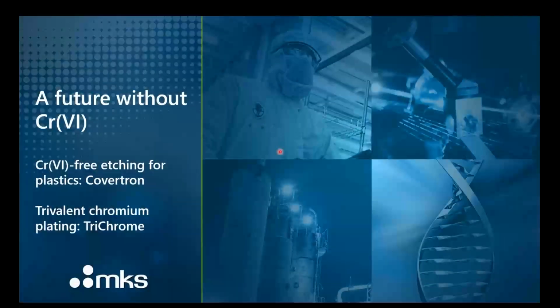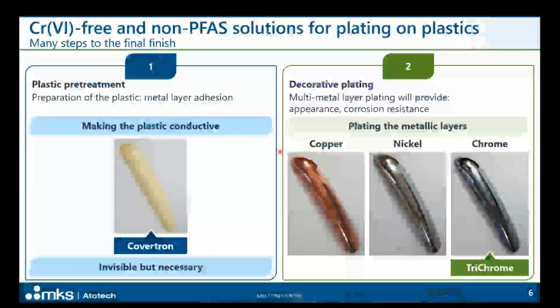So let's go to the future without chromium-6. For plating on plastics, there are several steps using chromium trioxide and PFAS. So for plastic, the first step that we need to do is to make it conductive or to metallize the plastic surface. In the industry, normally now is using chromium trioxide as the etching step, followed by palladium activation, electroless copper or nickel, and our Covertron process is a one-to-one direct replacement of chromium 6 etching. This is necessary for every plating on plastic step.